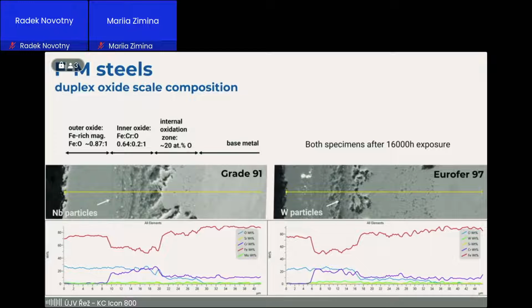It will develop a duplex scale that consists of an outer oxide that is magnetic, or it's an iron-rich spinel that's formed by diffusion of iron from the inner oxide outside and oxidized from the top, so this is a large grain. Very fine inner oxide has a very fixed ratio dependent on environment, on type of ferritic steel, on time of exposure, and there is only a difference between grade 91 and Eurofer that there is slightly increasing chromium towards the metal and oxide interface. There is also what we call the internal oxidation zone, that zone that contains 20% atomic of oxygen and goes deep into the material. In Eurofer, this zone is extremely large.